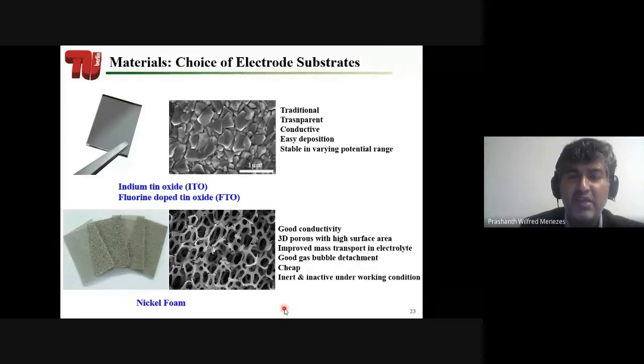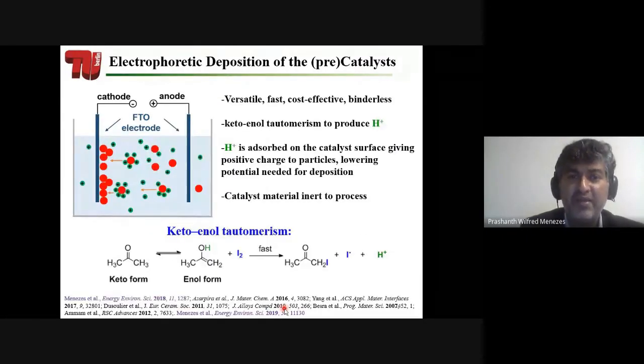Okay, now imagine that you have powder and you have a substrate. Now, how can we deposit the powder on the substrate? There is a simple method which we have been using for many years. This is called electrophoretic deposition. What you do is you use your FTO or nickel foam here as the cathode, and then you take your powder in acetone solution and you add a little bit of iodine.